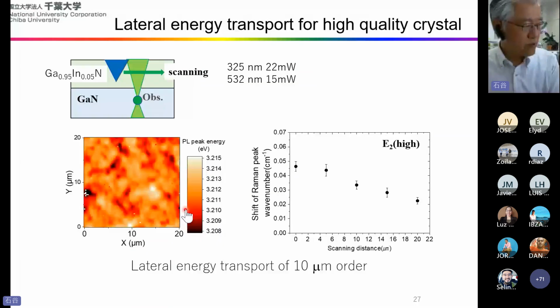And we can also monitor the lateral phonon transport. The shift of the Raman peak wavenumber means the temperature increase, and the temperature is decreasing from the heating position to outside of the heating position. A lateral energy transport on the order of 10 micrometers was monitored.